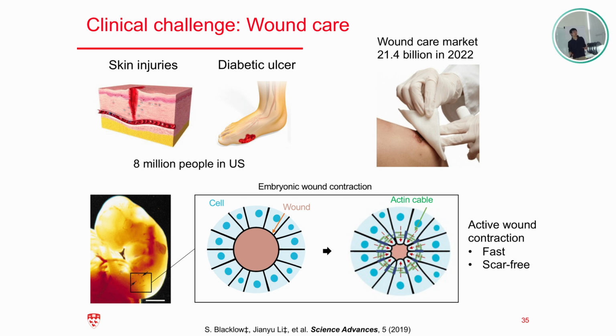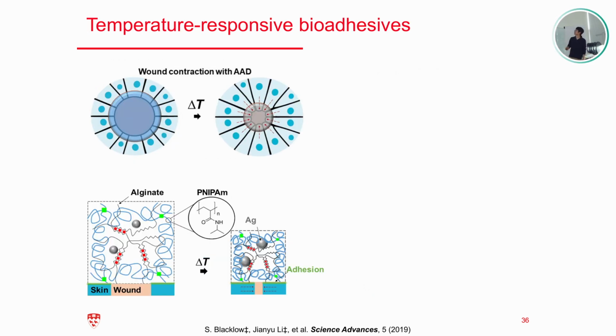So we mainly heal our wounds through regeneration. And how can we restore this superpower of our skin? Our strategy here is to leverage this adhesive platform. What we do here is that since we can stick our hydrogel to the skin quite well, we can further enable the contraction of this hydrogel. And through the contraction, it can actively promote the closure of the wound. And in order to do that, we will still do the trick with the adhesion, but most importantly, we need to add a new function like temperature sensitivity.